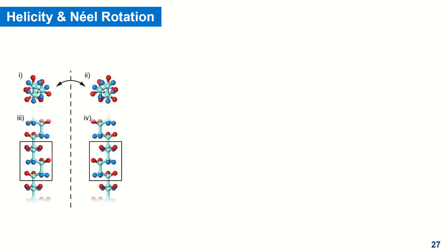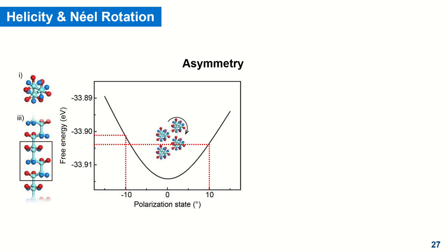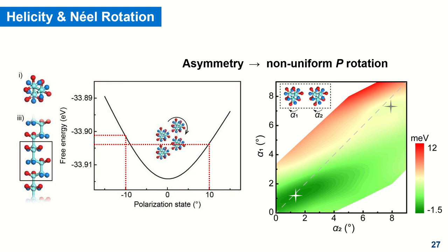One of them, which is left-handed, is chosen to do free energy calculation along different directions. They exhibit less energy when rotated collectively in one sense than the other. This suggests that the polar interaction is already asymmetric. We then calculate the relative free energy of a pair of helical chains. Each of them is rotated independently by an angle.